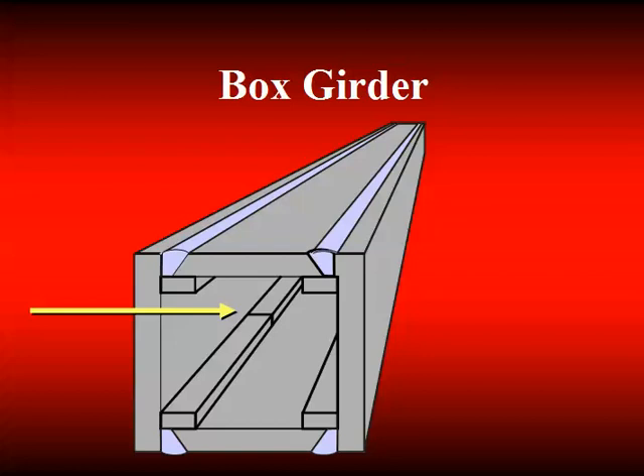And so when the box section is strained, the strain associated with this web is the same as the strain associated with that backing. Now we have stress through the backing until it gets to this interface between the two, and whatever stress is in the backing has to bounce out and then continue on. And we have a lack of fusion plane perpendicular to a stress field that acts like a crack. And certainly when subject to cyclic loading, and even in some cases subject to static loading, that's been the source of fracture initiation. Now this is also a code violation because the code says backing needs to be continuous for the length of the joint. The point here is here's backing, no secondary members in welded construction, and something that can be problematic.